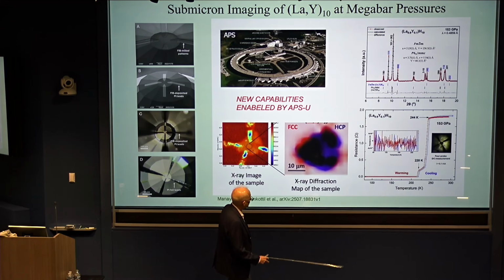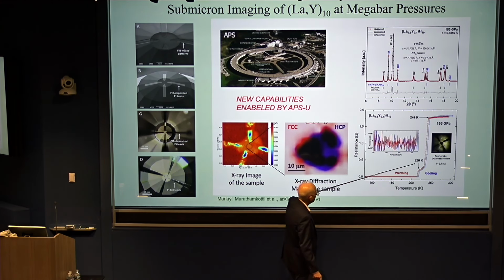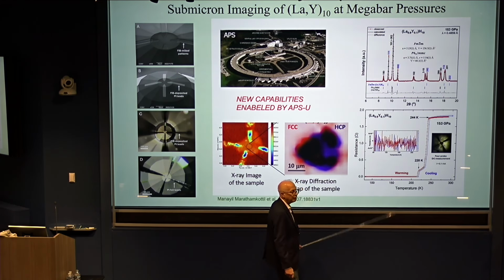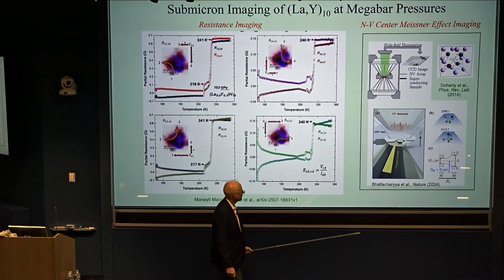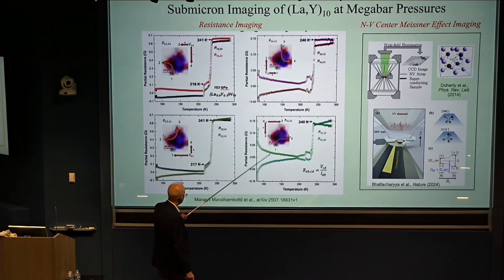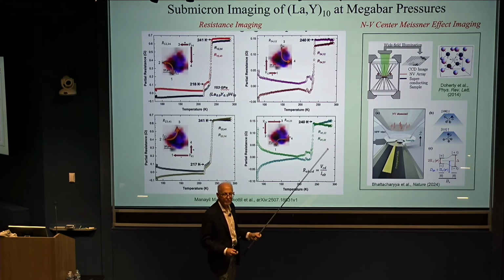And this is an interesting case because we see from our electrical measurements, there are two superconducting transitions. And we know from the diffraction, one is due to a hexagonal phase and one is due to a cubic phase. And so we have this beautiful map now, which allows us, in this sort of complicated slide, don't look at all the details, but the point is that we can map out the portions of the sample that are due to one phase versus another, so we can effectively spatially resolve the resistance in this measurement.